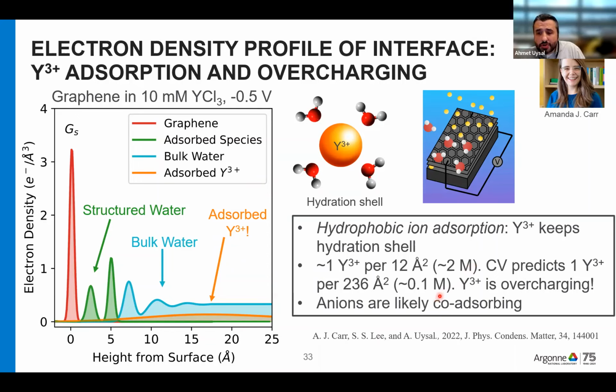And of course, CV is only measuring the total charge, and there will be anions accompanying the yttrium at the interface. So that is how you get the charge balance. But still, bringing that much yttrium to the surface, but not being able to get them very close to the surface, is a very interesting observation. And that is an important property of the graphene, because this is a pristine graphene with no functional groups, and therefore there's no way for these yttrium ions to coordinate at the interface. That is probably why they are adopting this interesting distribution at the interface. And we are now working on the system. We had a beam time recently, so we are getting more interesting results about this system. Hopefully, next time we can talk about that.